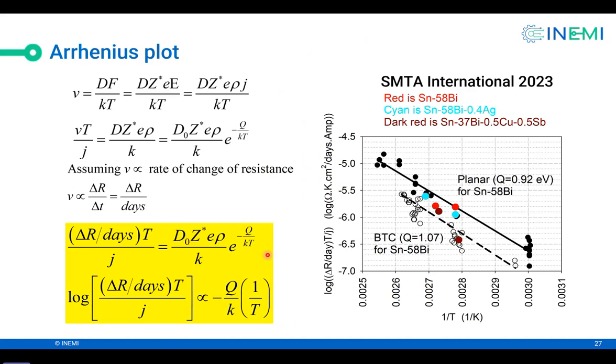Okay, so I have to explain why we're using log of rate of change of resistance times temperature over J. I won't go through these calculations, but this is straightforward physics, and we end up with log of rate of change of resistance times temperature over J proportional to a constant Q over K times 1 over T. Q is the activation energy, K is Boltzmann's constant, and so you have the negative value here. That's why the curves have negative slope. We're showing solid black dots and some colored solid ones. This is for eutectic tin bismuth with no alloying element.